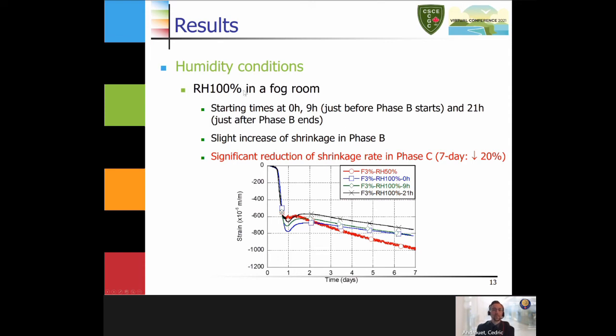So what happened when we put the specimen at a relative humidity of 100%, typically in a fog room? We see that no matter the time at which we start the curing, we have a slight increase of the shrinkage in phase B. Slight increase, but more interesting is that we have a significant reduction of the shrinkage rate in phase C, as well as the swelling observed at the beginning of phase C that is increased when we have a relative humidity of 100%. So the increase in shrinkage is compensated by the swelling, and the shrinkage rate in phase C is reduced compared to the relative humidity of 50%.